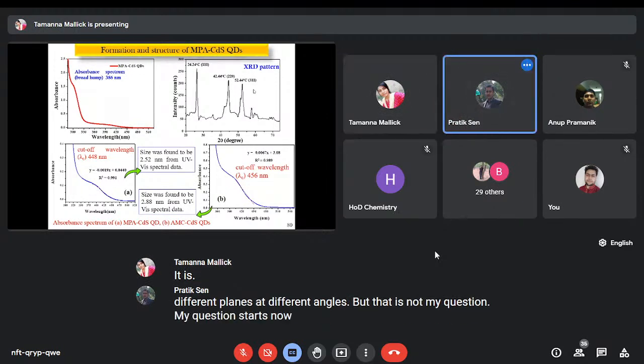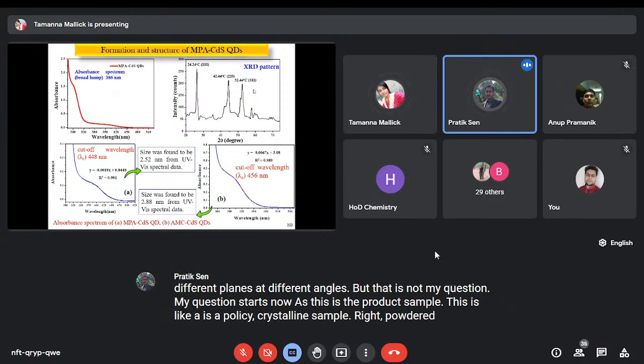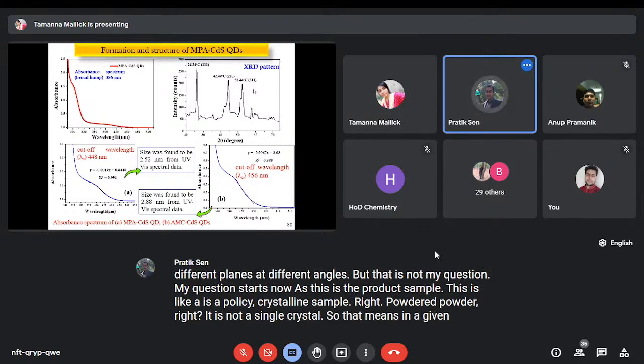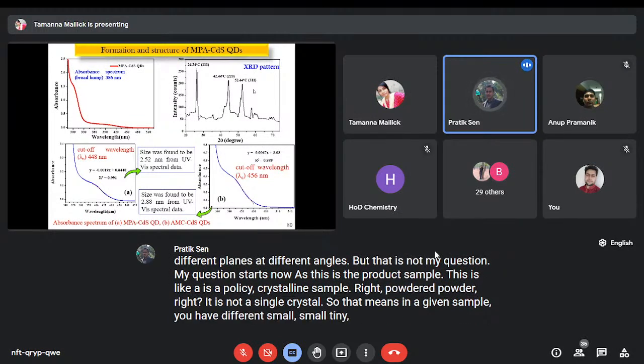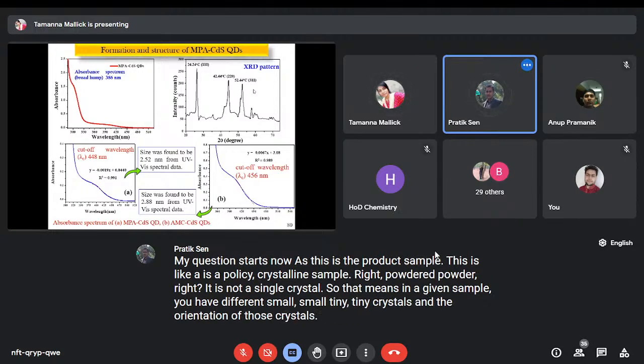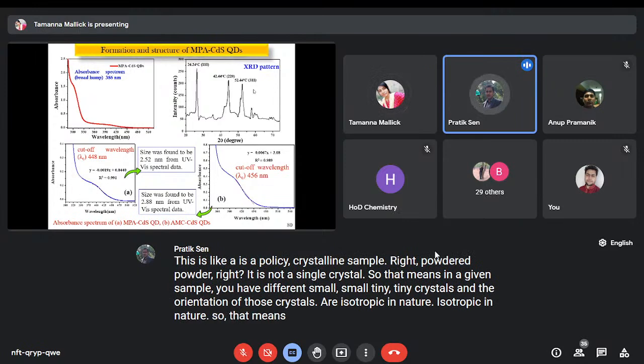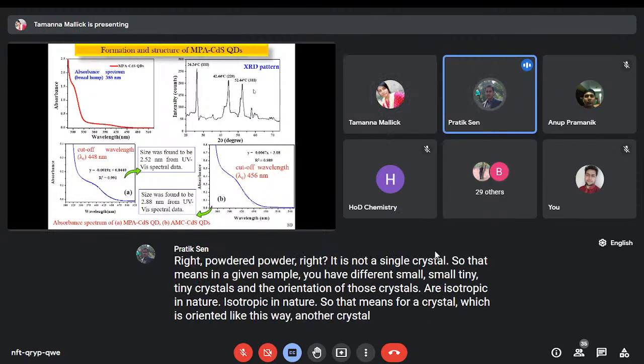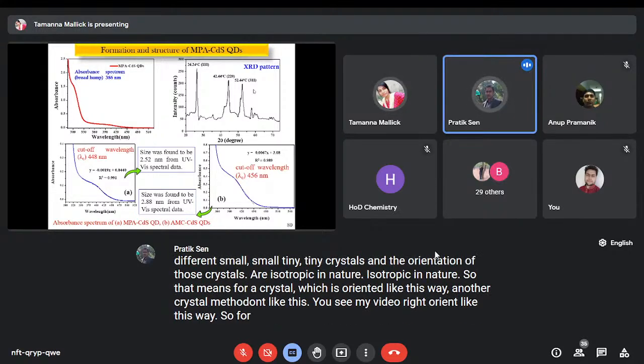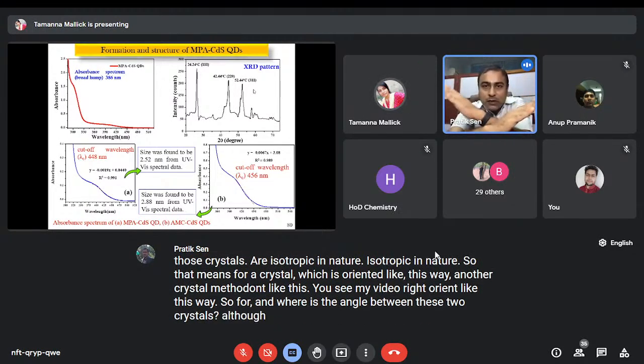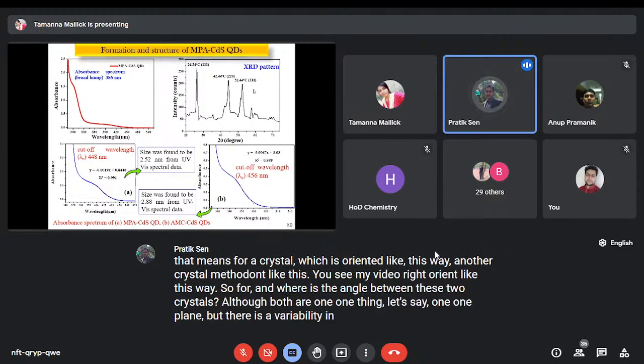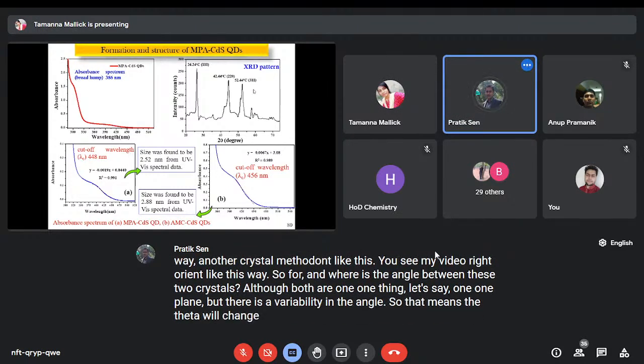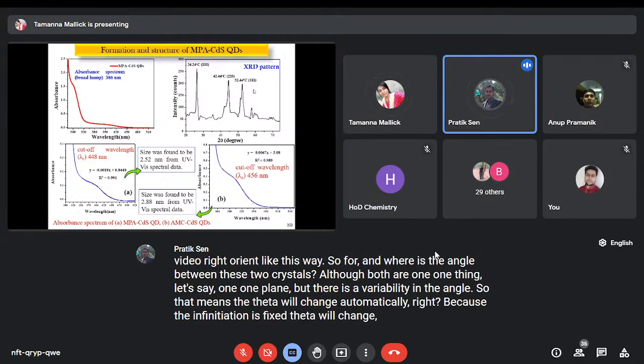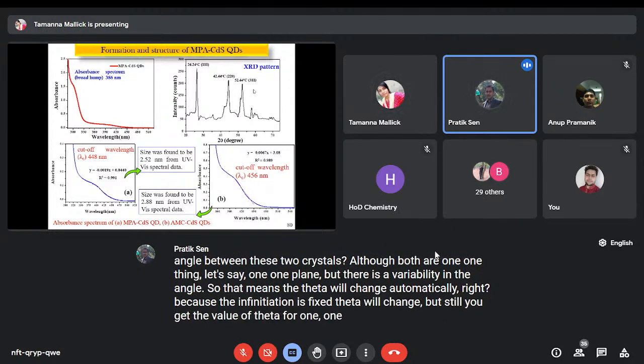My question starts now. As this is a powder XRD sample, this is like a polycrystalline sample, right? It is not a single crystal. So that means in a given sample, you have different small, tiny crystals, and the orientations of those crystals are isotropic in nature. So for a crystal which is oriented this way, another crystal may be oriented that way. You see my video, right? And there is an angle between these two crystals. Although both are the 1-1-1 plane, there is a variability in the angle. So the theta will change automatically, right? Because the incident radiation is fixed. The theta will change, but still you get the value of theta for the 1-1-1 plane at a particular angle.